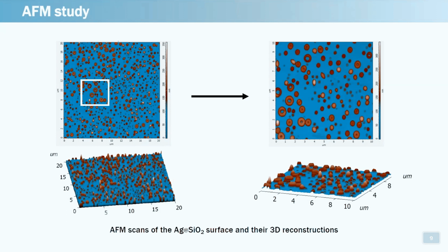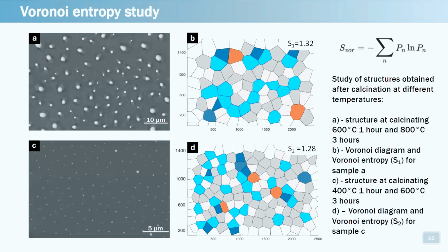This was followed by atomic force microscopy study. The method was used to determine the shape of micro and nano agglomerations and their heights above the surface. Thus, we understand that our microagglomerations are of the shape of hemispheres and are approximately 200 nanometers high above the surface. At this stage, structures were studied by Voronoi entropy calculation.